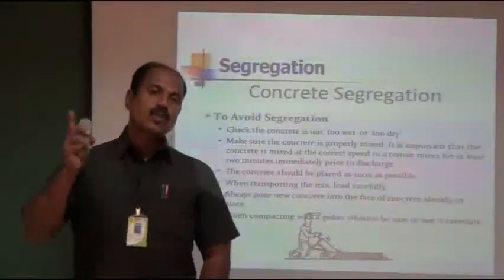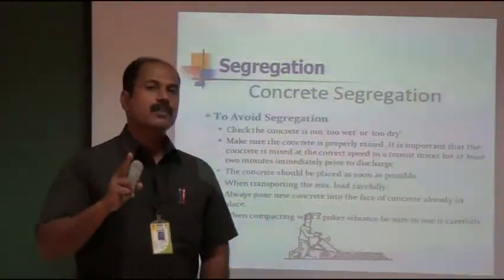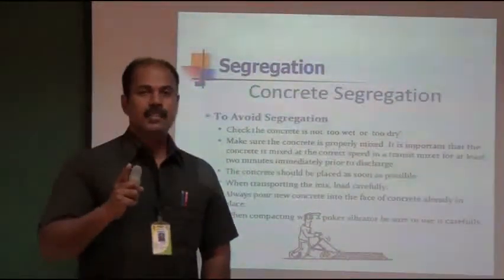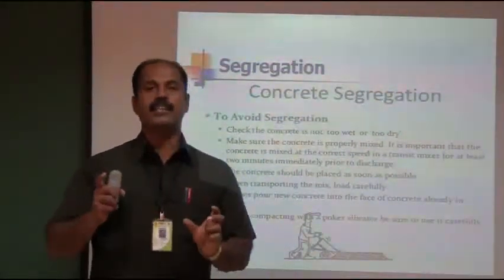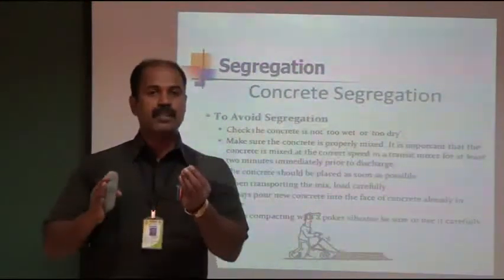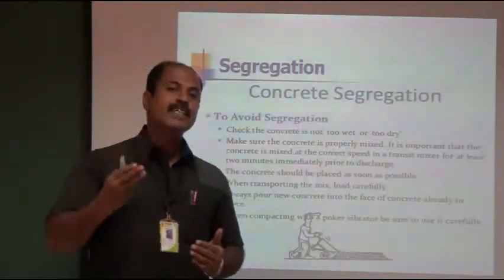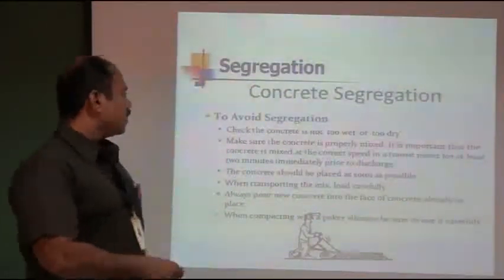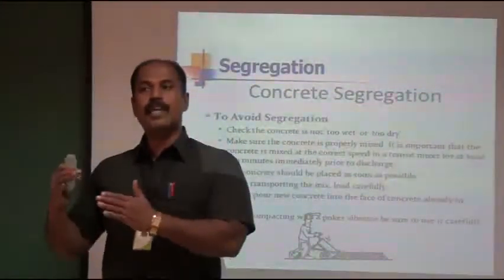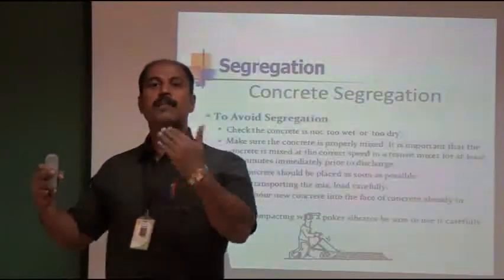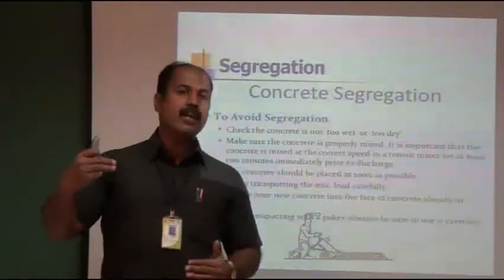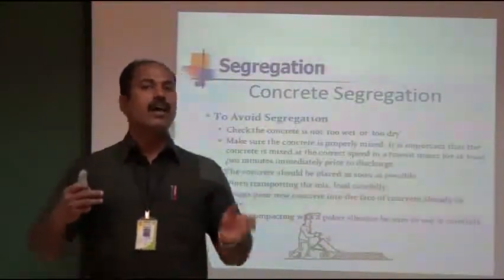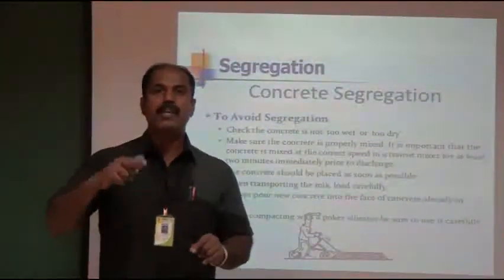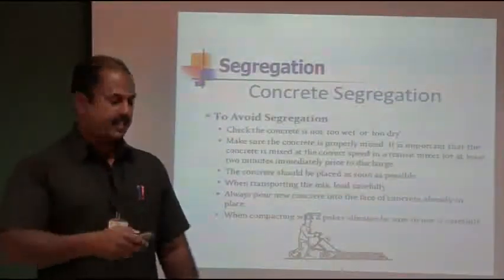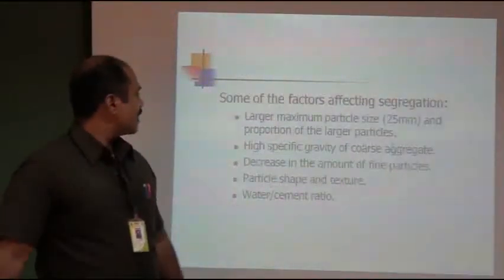First, concrete that is either too wet or too dry leads to segregation. Second is the selection of the aggregate: maximum size or minimum size aggregate selection affects segregation. Third is the transporting of the concrete. Suppose we transport the concrete from one place to place it elsewhere; beyond 100 meters, segregation will occur. And fourth is over vibration. Vibrating beyond the limit causes segregation, so that is the reason segregation occurs.